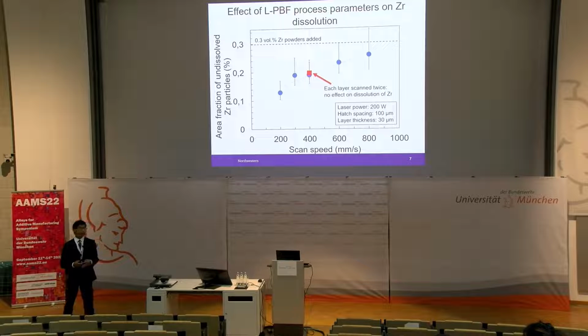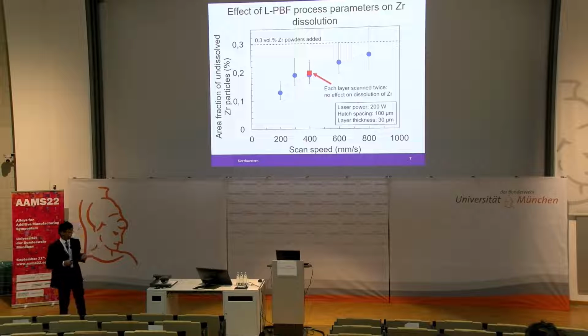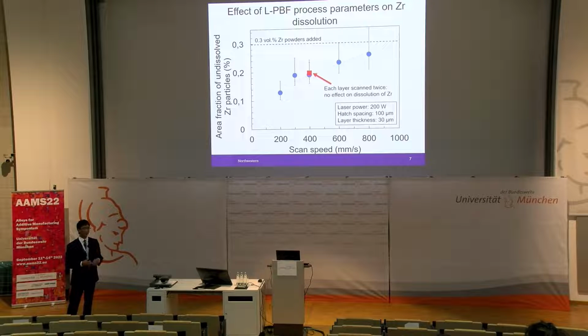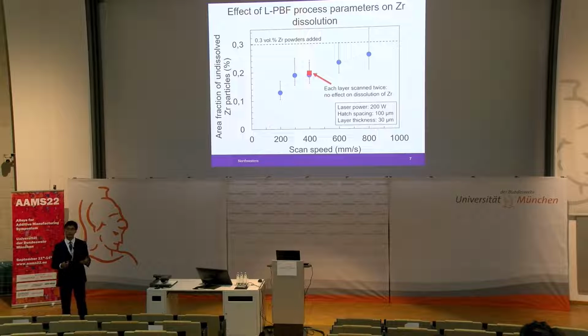The other parameter that I'll talk about is the effect of scan strategy, in particular when we scan every layer twice. What we had expected is that by scanning every layer twice, the zirconium particle is spending longer time in the melt pool, and therefore we achieve greater dissolution of zirconium. However, we see that this is indeed not the case.